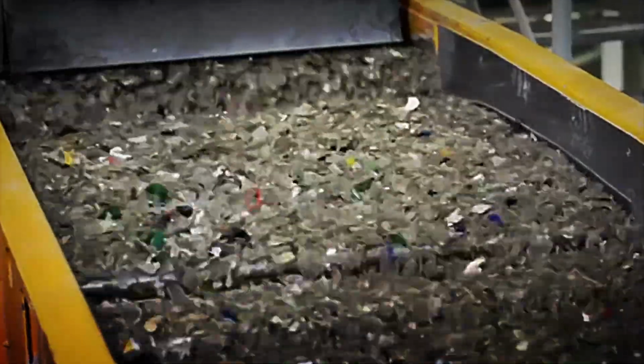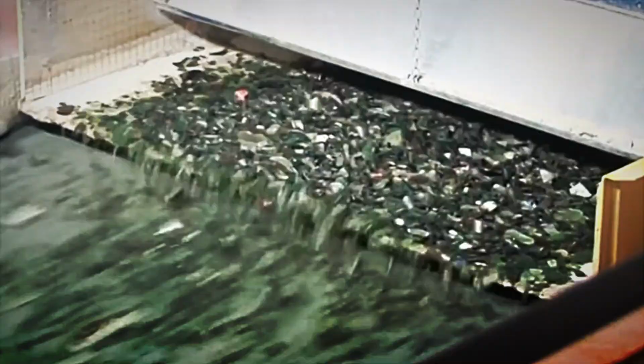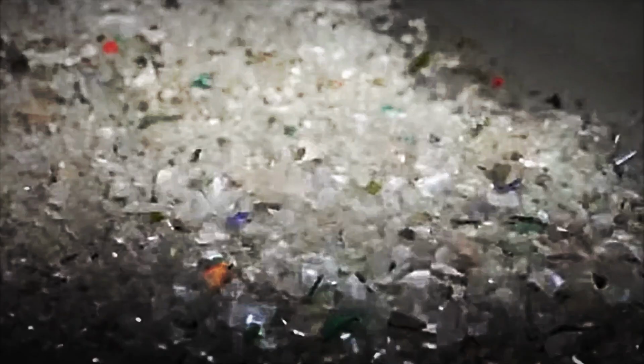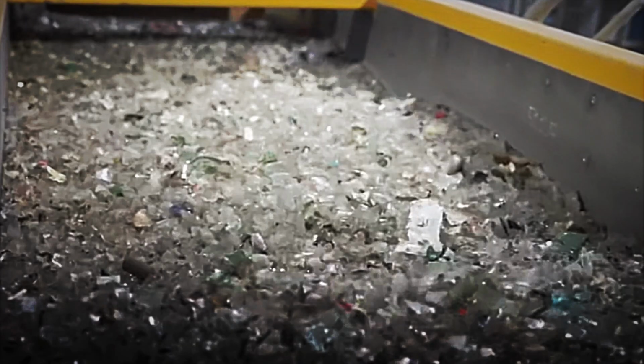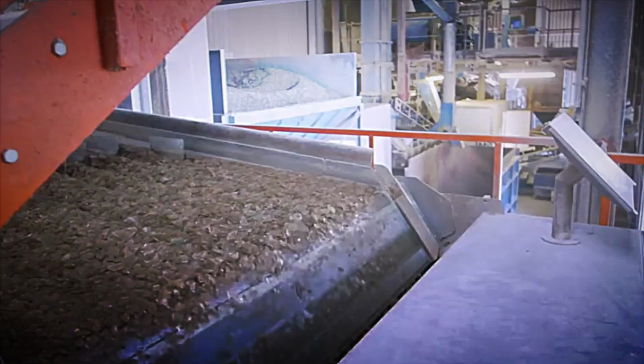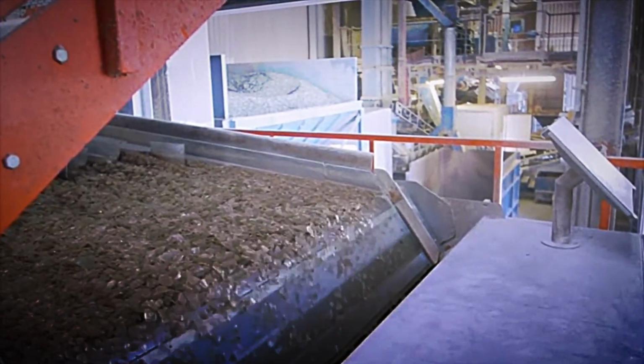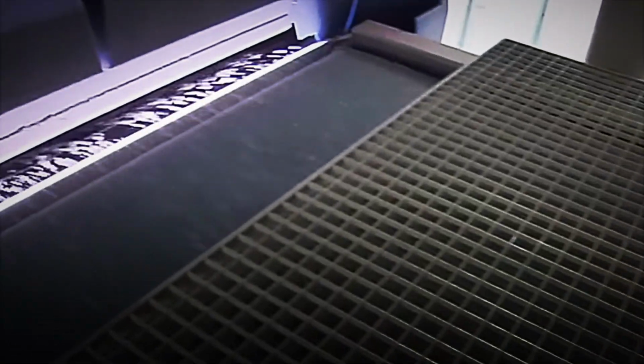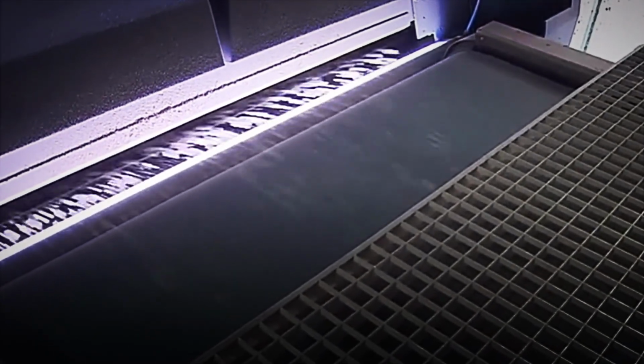The cullet is then sent to automated systems for color sorting. The fragments fall onto high-speed conveyor belts and pass through laser sensors and industrial cameras that analyze each piece in fractions of a second. Clear, green, amber glass and even contaminants like ceramics are instantly identified. Jets of compressed air are activated with millimeter precision, diverting each fragment to its corresponding channel. The entire system operates without interruption, processing tens of thousands of pieces per minute. This precise sorting is essential, as even a slight mix of incorrect colors can affect the optical quality of the recycled glass. Once sorted, the cullet is transported by belts to the mixing system.